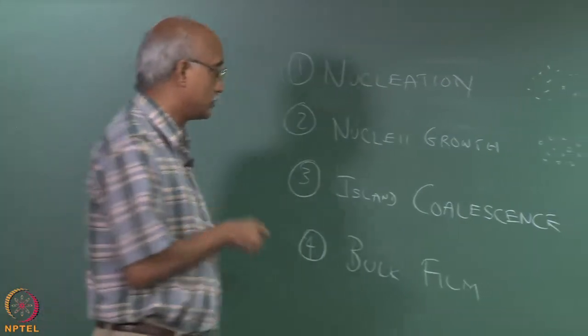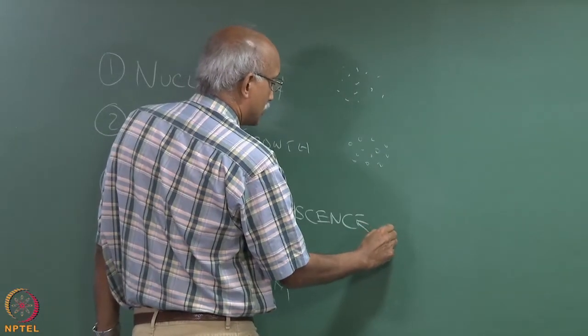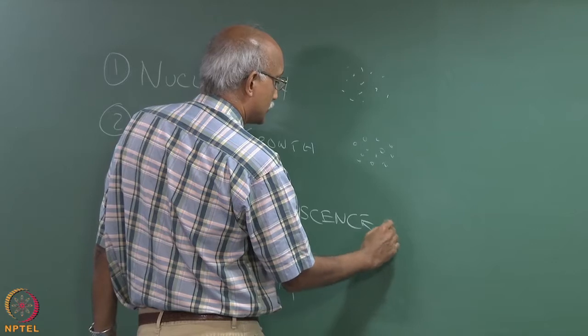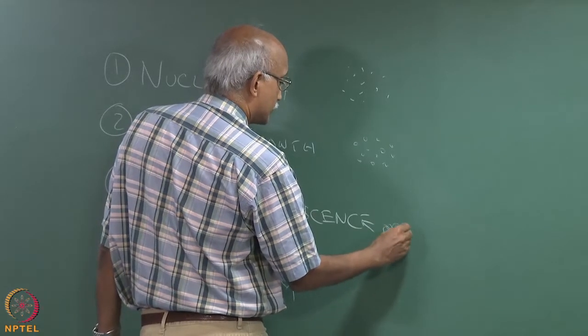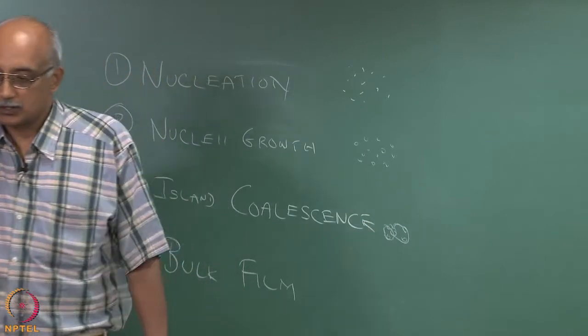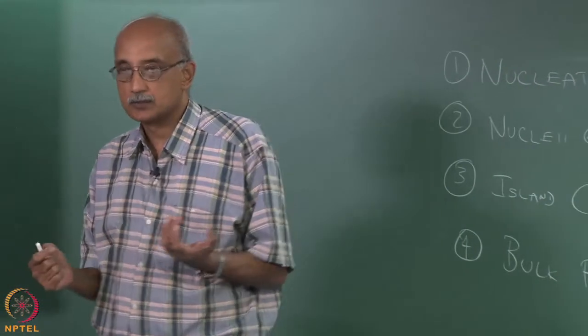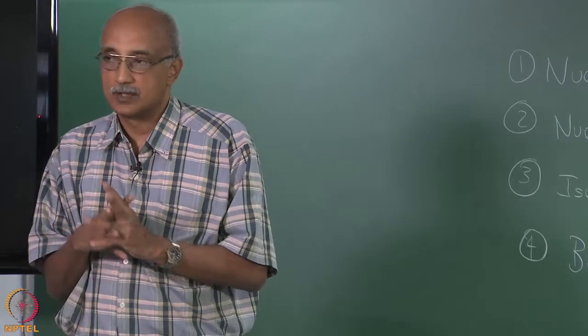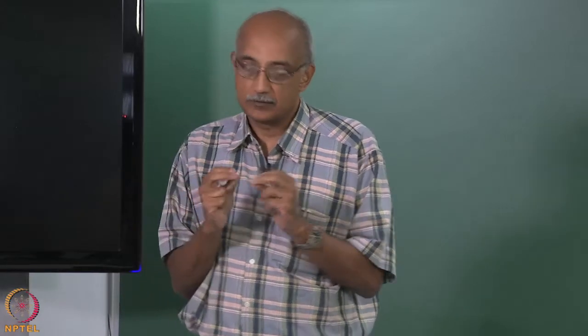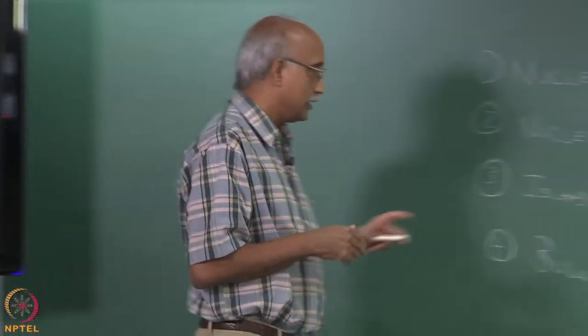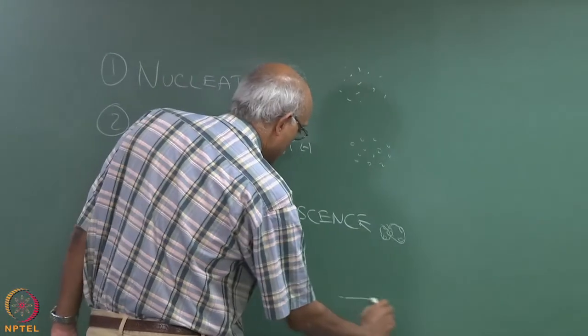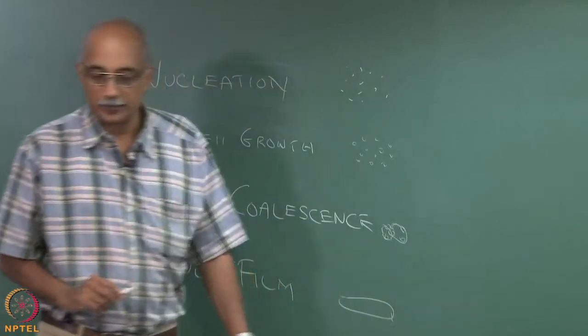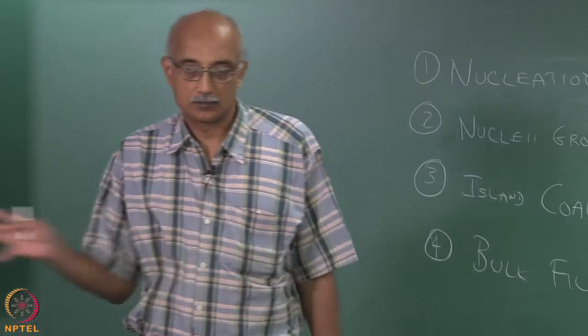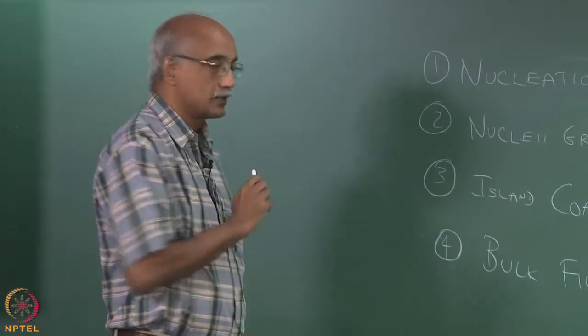The third stage, island coalescence, is where a few of these start finding each other as they grow large enough and forming these islands, which is still not a continuous film, but now you are starting to form clusters of molecules attaching together to form these isolated and very, very short films. Finally, the bulk film stage is where these islands start to coalesce together and you eventually wind up with a nice continuous, contiguous film.